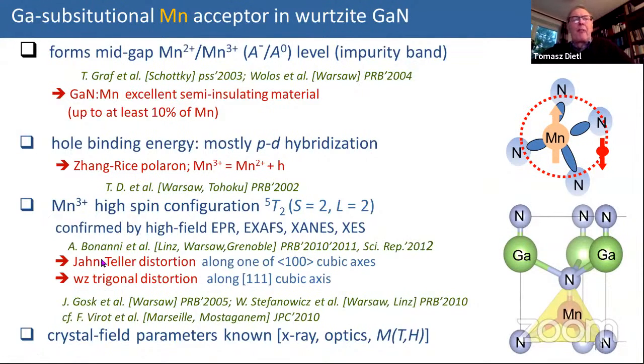And we know also from the physics of magnetic impurities, transition metal impurities in various substances like oxides, that in the case of non-zero orbital momentum, we have Jahn-Teller distortion, because the system lowers its energy by lowering symmetry if the orbital momentum is not zero. And also, it's a wurtzite structure, so we have trigonal distortion along one cubic axis, because it's by definition a wurtzite structure. And the crystal field parameters describing this impurity are known from X-ray, optics, and magnetization studies. So we know a lot about this manganese in gallium nitride.